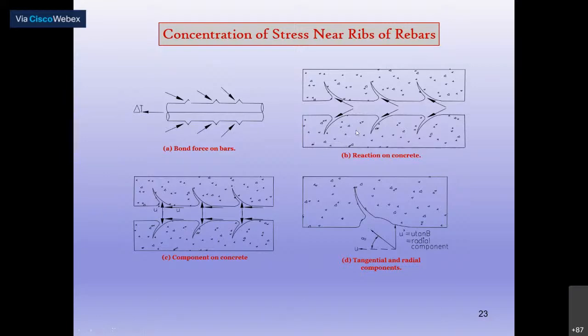We studied this experimentally in reinforced concrete beams subjected to cyclic loading with a defined maximum and minimum stress. We found the micro cracks initiated like this. If the bond stress is very low, within the limit, these cracks would not have formed. But when the bond stress exceeded, this is the component normal to the inclination, the horizontal component is the bond stress, and the vertical component is the radial stress. So one of these components will be causing cracking.